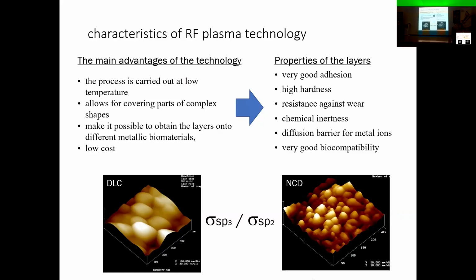We can obtain different kinds of carbon coating. So I told you before about nanocrystalline diamond. It means it's a very thin coating, but it consists of nanocrystals of the sizes of tens of nanometers. So that's nano. And it is almost pure diamond, but almost. If it were pure diamond, it would break easily. But because it has some sp2 phases, it's better, so it doesn't break. It has better mechanical properties. Also, it has very good adhesion to the surface.